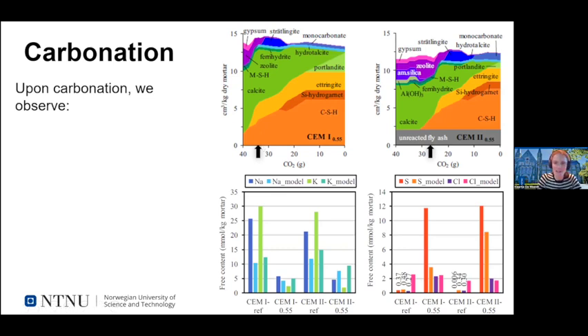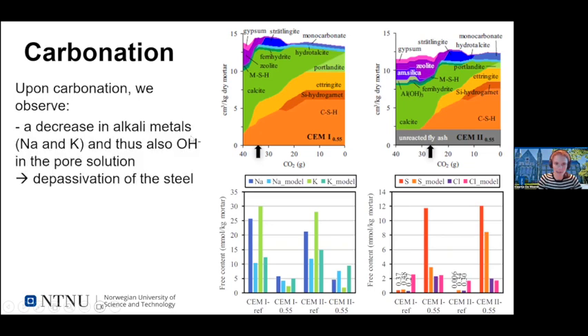And this is where Gilles used his cold water extraction technique to try to obtain pore solution composition in these carbonated mortars. And we have compared the experimental results with the modeled ones. And what we could see, first conclusion is quite obvious. When we compare the references, non-carbonated, with the carbonated ones, and the blue bars are for sodium and the green for potassium, we can see a decrease in the sodium and potassium in both investigated cements.